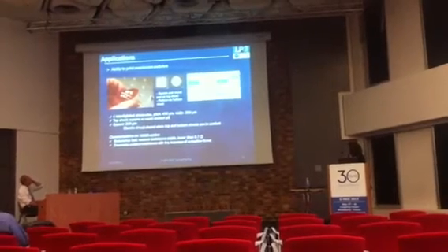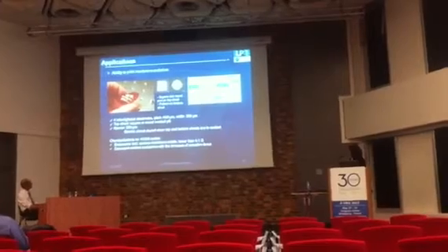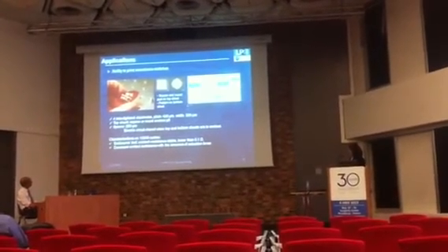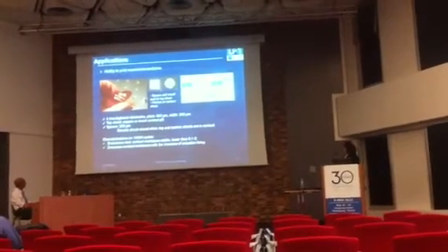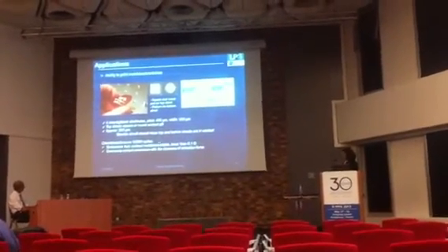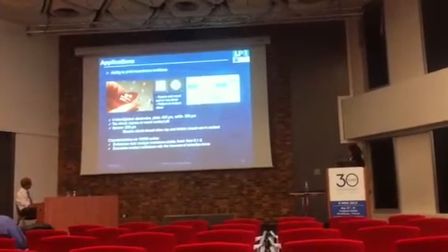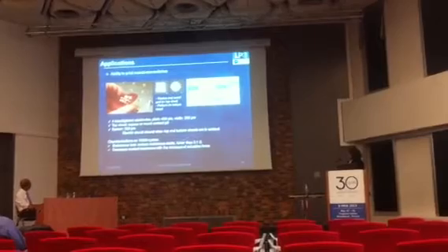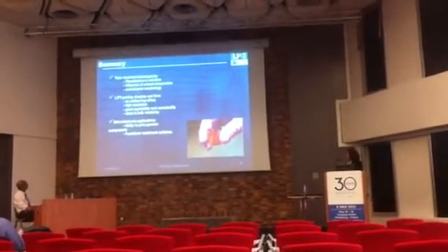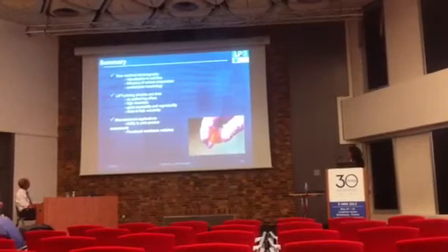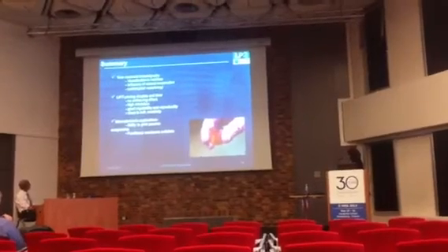And when we push here to allow a contact between button and electrode, we can measure the contact resistance, and we can see that the contact resistance is very stable for a lot of cycles, and it decreases when we increase the actuation force.